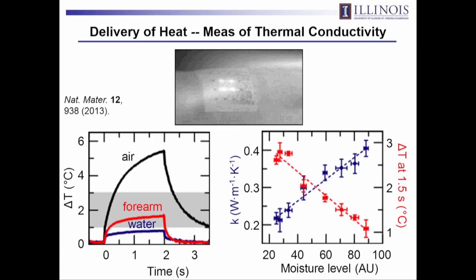And that's interesting because it turns out that the thermal conductivity quantitatively correlates in a linear way to the moisture level or the hydration state. So now you can throw out your corneometer and you can use this type of patch to measure hydration state. And you can see that correlation here. So this is thermal conductivity measured from the time dynamics of how the skin heats up when thermal power is delivered to its surface and how it cools down when that power source is eliminated. So hydration. You can also determine blood flow.